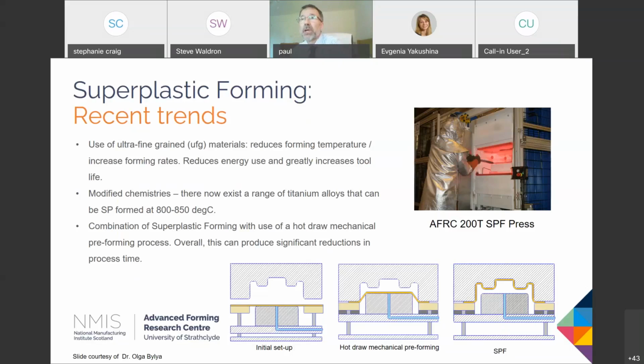The other thing that people have been looking at over the last few years, and some of our colleagues at TIMET have spent a lot of time working in this area, is modifying the chemistry of titanium to actually reduce the SPF temperatures. We can now form a range of titanium alloys in the temperature range that you see there, 800 to 850 degrees C. Nice example of that would be Ti-54M.